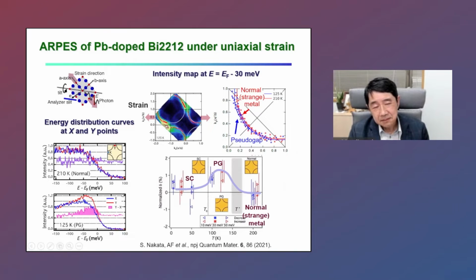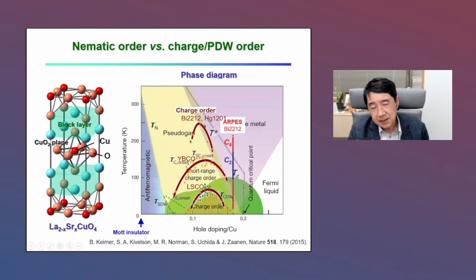So we have done ARPES experiments, but let me skip that of YBCO, BISCO under uniaxial strain. But let me just show the results. The symmetry breaking occurs in the pseudogap phase, and symmetry recovers in the normal metal phase, as well as in the superconducting phase.